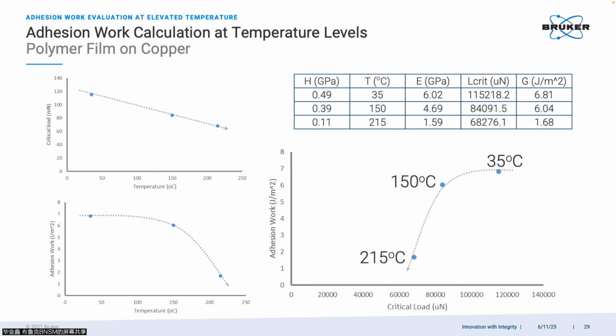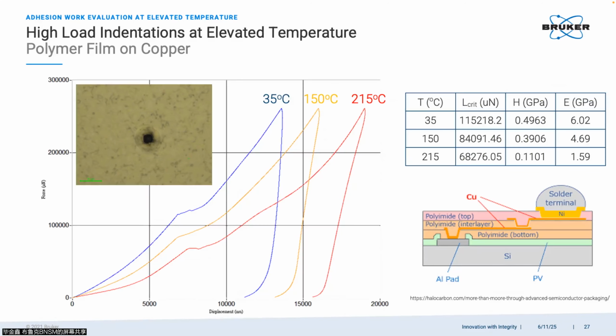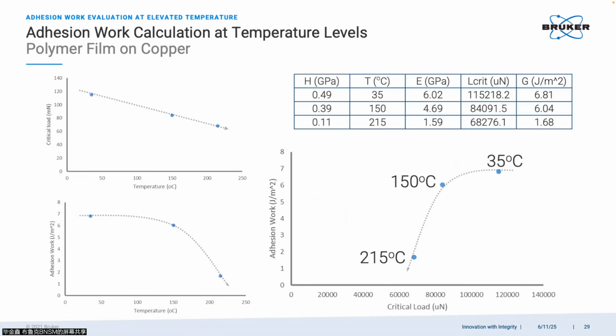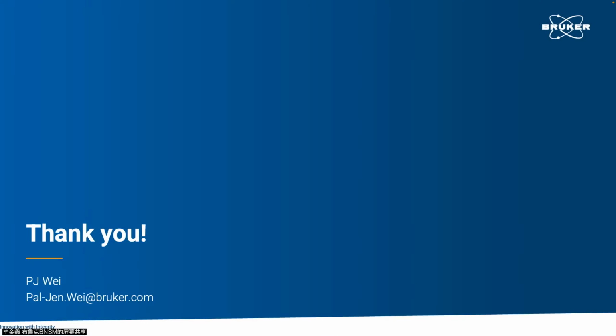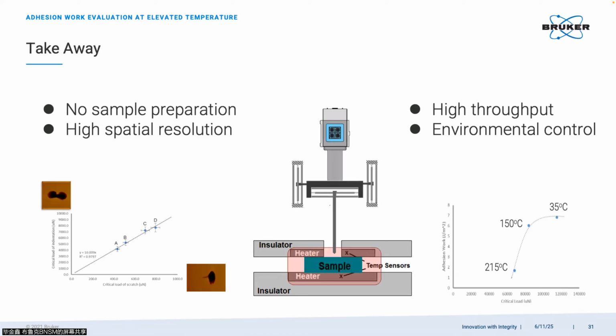For metrology, this is good news. But for manufacturing of copper and polyimide, it is very bad news. That means when you have a high temperature process up to maybe 200 degrees Celsius, your interface will get much weaker than at room temperature. So this is the final example application I would like to share with you about interfacial bonding metrology at elevated temperature. This is the takeaway: today we talked about indentation together with scratch, of course, focusing on the intrinsic mechanical properties of the top layer and the interfaces.